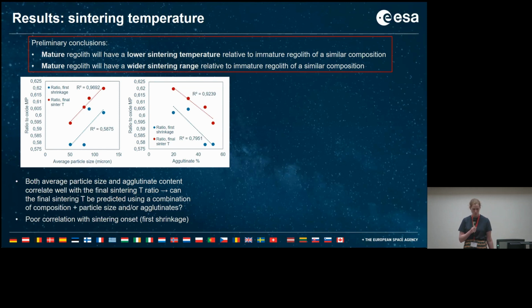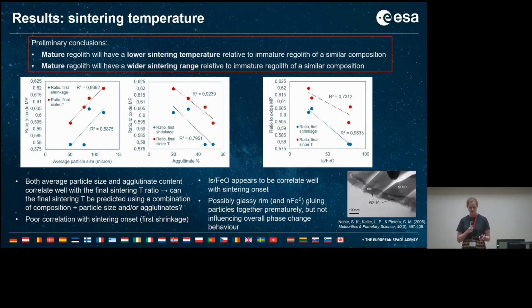However, we see quite a poor correlation with the sintering onset, so the first shrinkage of the material. And then when we compare the ratio to the proportion of nanophase iron, there we see a better correlation with the sintering onset temperature. This possibly suggests that the glassy rims on these mature particles are gluing particles together prematurely, but not actually changing the overall phase change behavior of the material. That might be why they stick together earlier in the process.